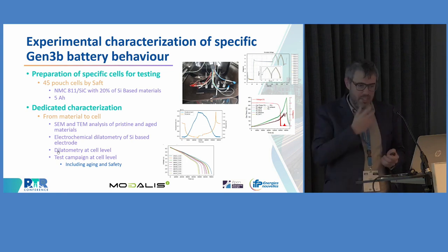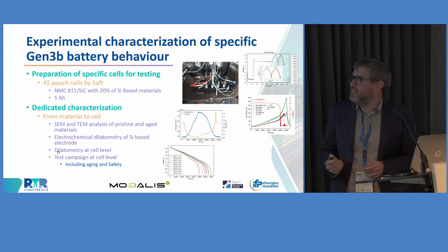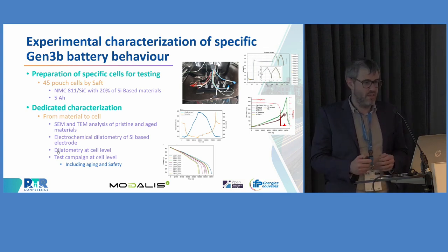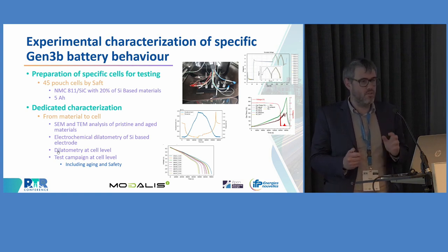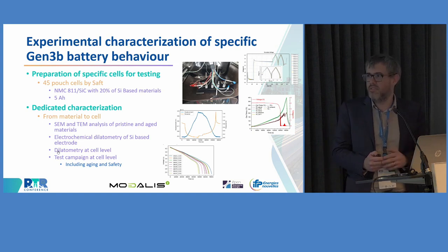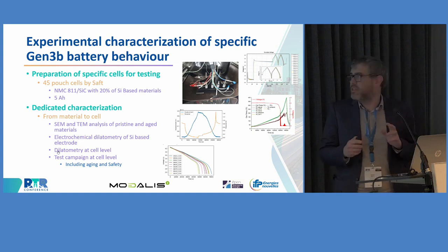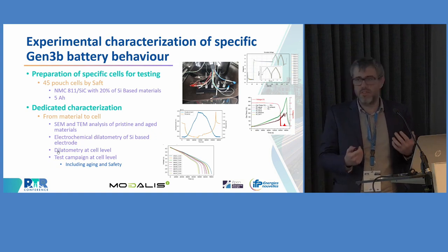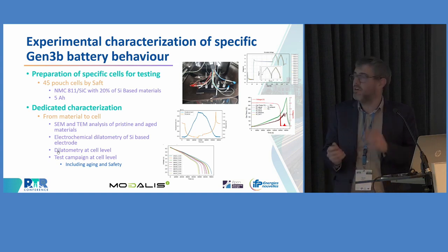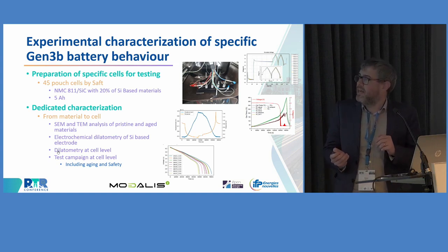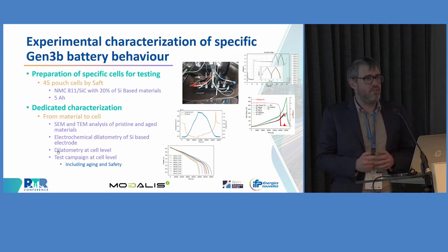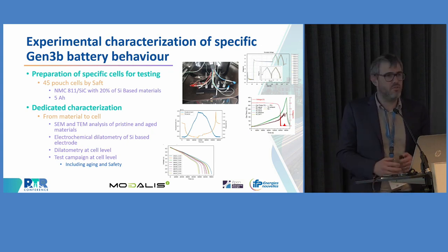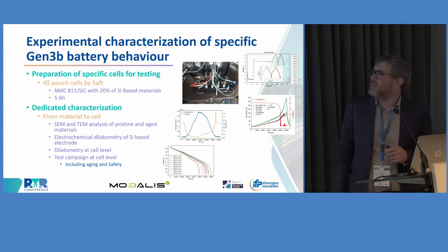So SAFT created some cells that were relevant for our project. So it was NMC811 silicon oxide graphite cells. And we wanted to have a huge impact of silicon. So we aimed at 20% of silicon in the negative electrode. So 20% was a way for us to ensure that we had sufficient volumetric expansion at the electrode level and see the impact of mechanical behavior on the electrode. We resulted with 5 ampere hour cells, so it was less than expected, but due to technical challenges, it was a good result to get these cells and make them work.